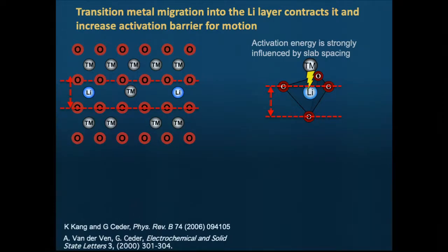So now you can see if the spacing here is large, then these ions can stay far away from each other, and you have good lithium mobility. If you condense the structure by making these planes come together, you increase the activation energy for lithium, and you have no motion anymore.